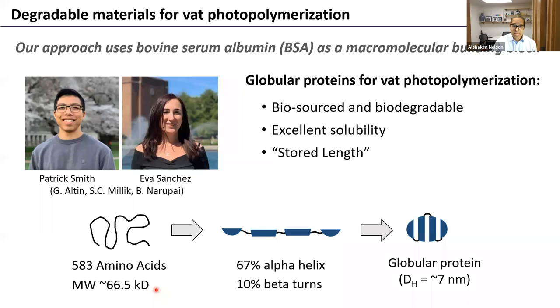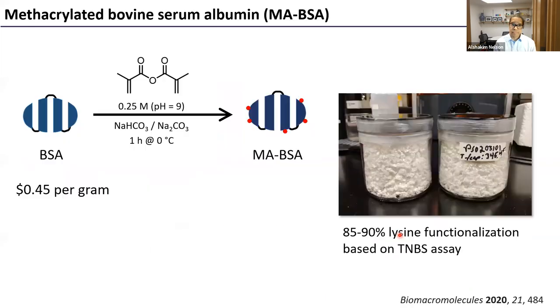66.5 kilodaltons. And this linear chain can be folded into a very compact globular structure, almost like a nanoparticle. But we can take this structure now and modify the surface to have it be compatible with 3D printing. So the BSA we buy by the kilogram, and we can take it and do a one-step methacrylation of the available lysines on the surface to produce a methacrylated BSA, or we refer to it as MABSA. And we do this on a 40 to 50 gram scale in a single batch.